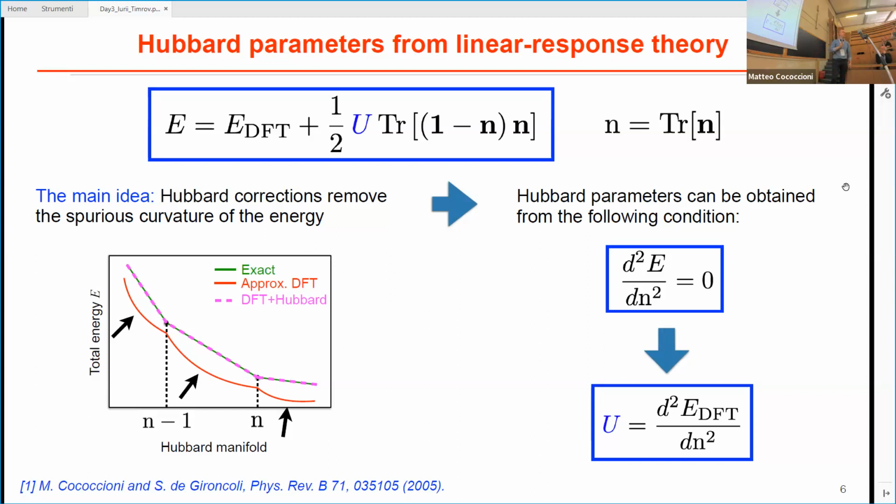And actually, another thing that I would like to highlight, if you examine this expression, it's very interesting because what this correction does, it removes the quadratic term. So you remove n squared, so you remove this parabolic-like behavior, and you're adding plus 1 times n. So you're putting in the linear behavior. It's very interesting. Actually, this was derived starting from the Hubbard model. We have a Hubbard-like term minus a double counting term in the fully localized limit. But very interestingly, the final expression has a lot of physical sense and meaning.